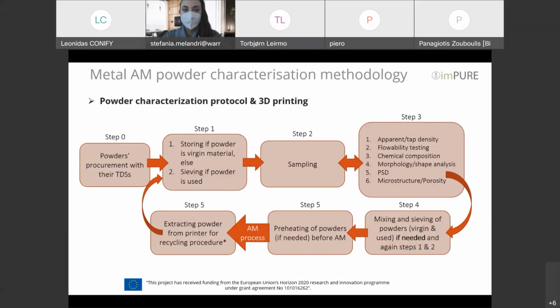So this is the overall workflow of the powder. We procure powders with their technical data sheets. We store the powder if the material is virgin. If not, then we have to sieve the powder. If it's used, we have to know in how many cycles it has been used. And then we do our sampling based on an automatic rifler. And in step 3, we run our analytical techniques and experiments in order to define the apparent and tap density, the flowability, the morphology, and the particle size distribution.